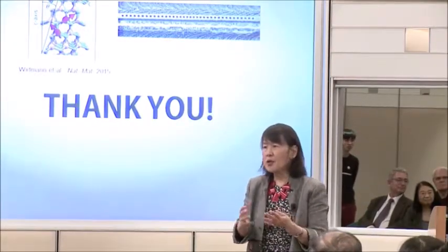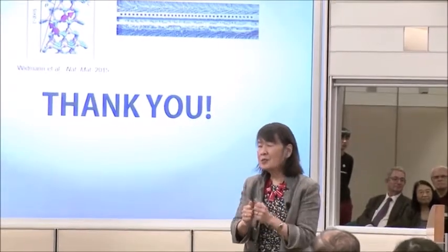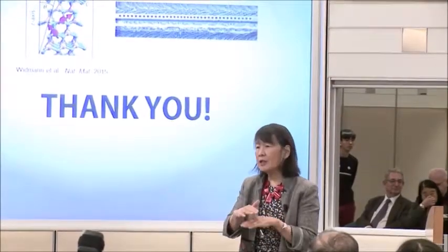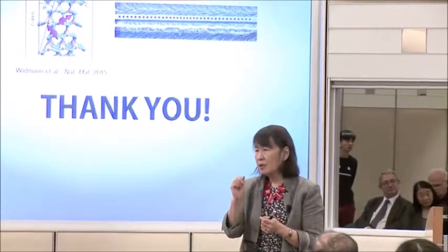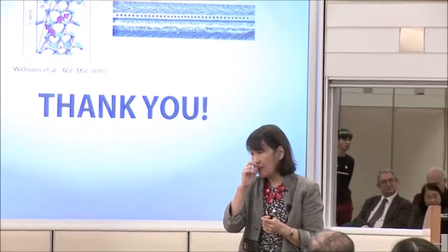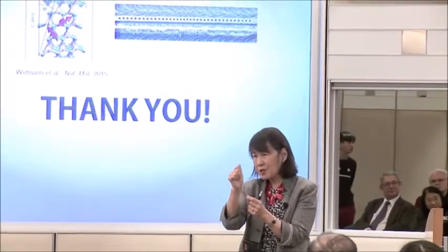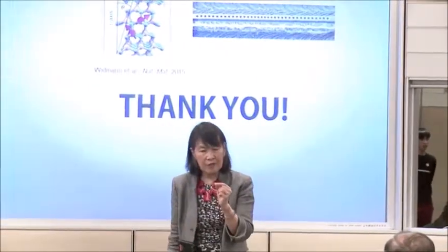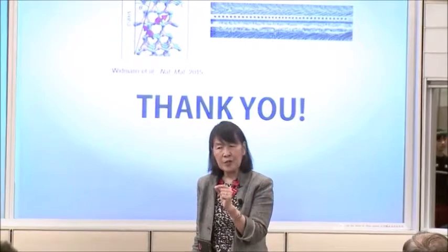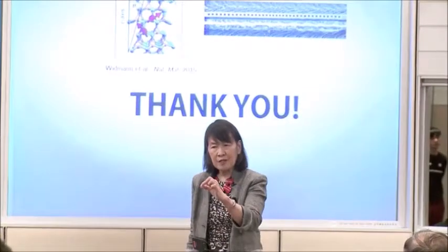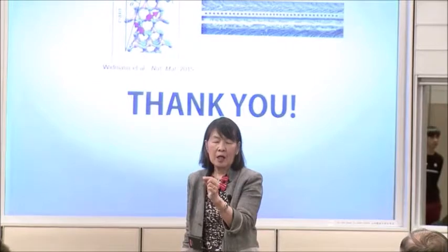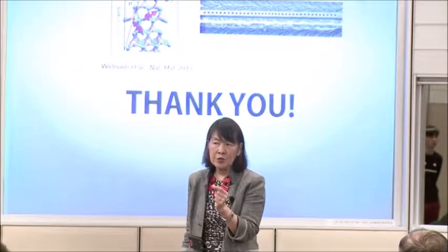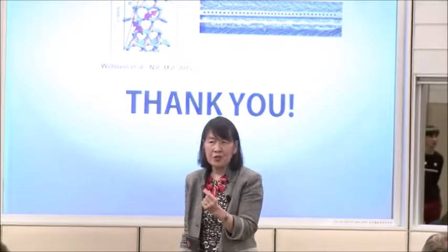So he said, let's just try annealing. When we tried annealing, we saw something very interesting: when you anneal, there is some healing of the resultant material, but there's some diffusion of the defects. And actually some of the peak heights increased. Right now we're exploring, although it may be very difficult, whether we can do something strategic by placing the defects almost in the right place, and then understanding the diffusion process enough to do some kind of diffusion to nudge them into the right place.